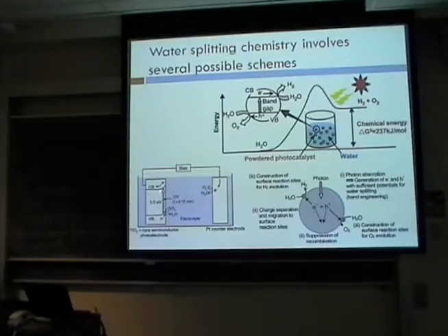And for the reaction where you produce hydrogen, you're going to need electrons that will want to flow from the conduction band to a potential that's somewhere inside the band gap. And this actually shows, I guess, a two-catalyst device where you get electrons flowing to do the reaction over here at this electrocatalyst. It's not actually even a photocatalyst.